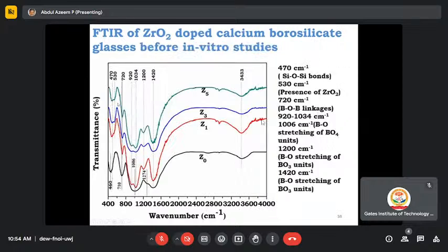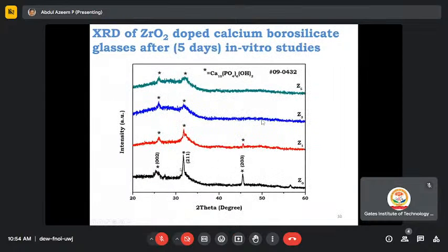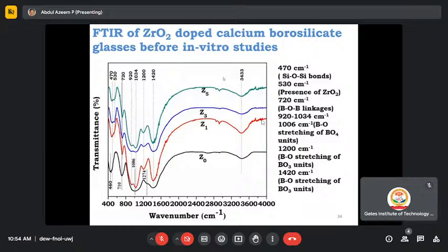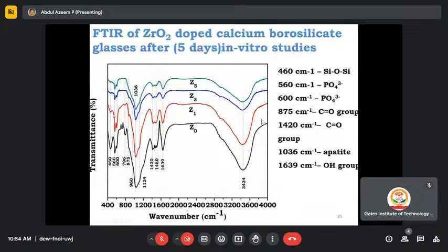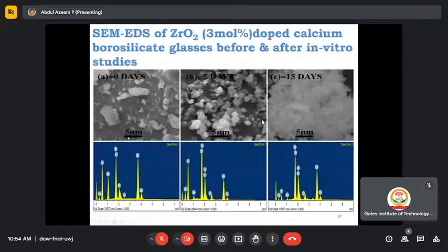So not only with the XRD are we confirming that these crystalline peaks correspond to the hydroxyapatite layer, the formation of a layer on the surface. I can say this is the bioactive nature of your material. With FTIR also, we can confirm whether the material is bioactive or not by means of these functional groups. Similarly, if you see here, this is a SEM image of your material.